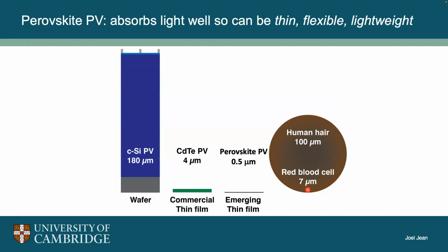In terms of why they're operating very well, these materials absorb light really well, but they're extremely thin. If we look at crystalline silicon, a typical crystalline silicon cell is about 180 or 200 microns thick. It has to be extremely thick, and this is because silicon actually doesn't absorb light very well. It's got an indirect band gap. So effectively, you need a very thick slab to be able to absorb the light very well.